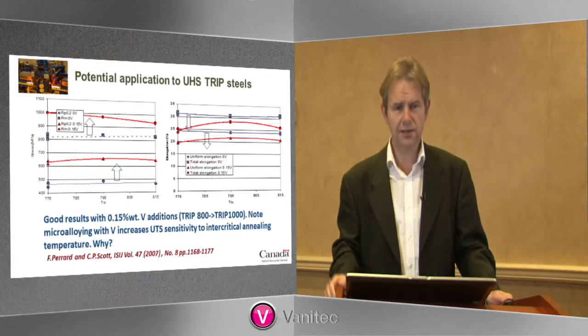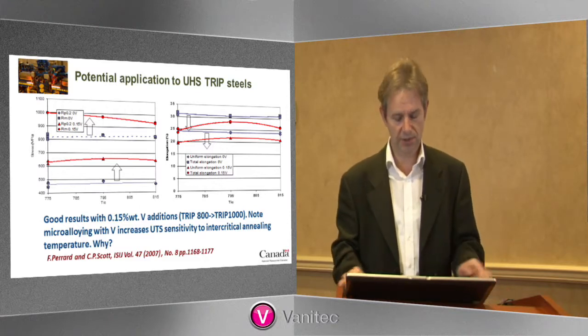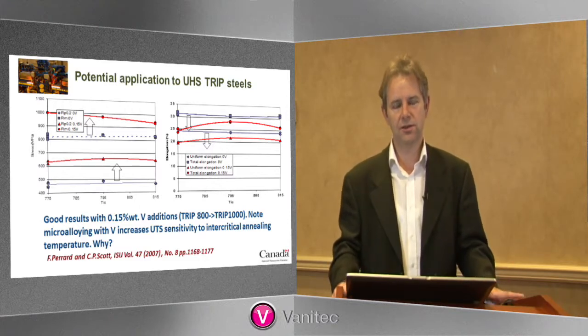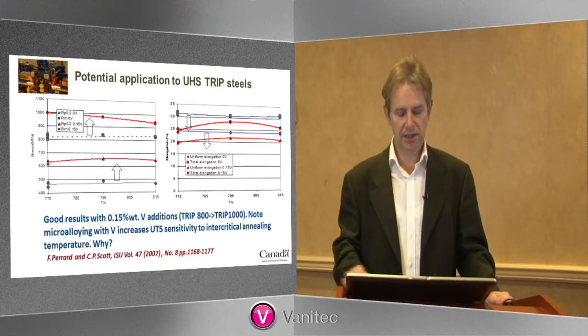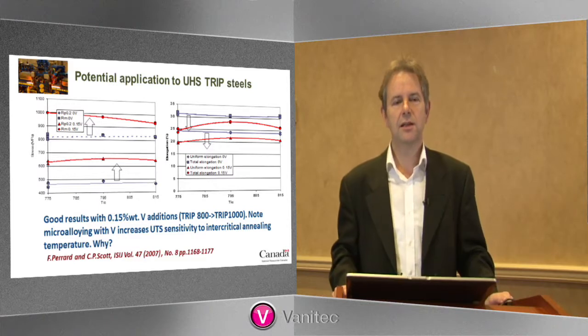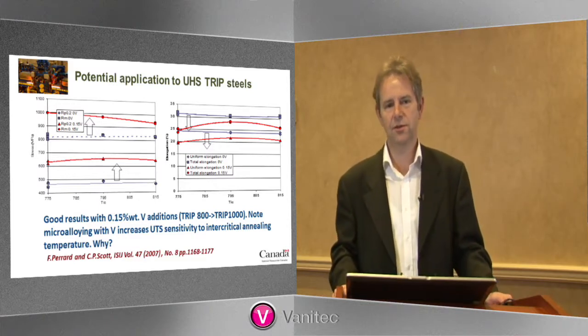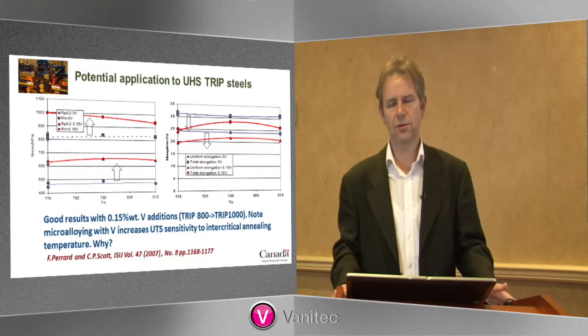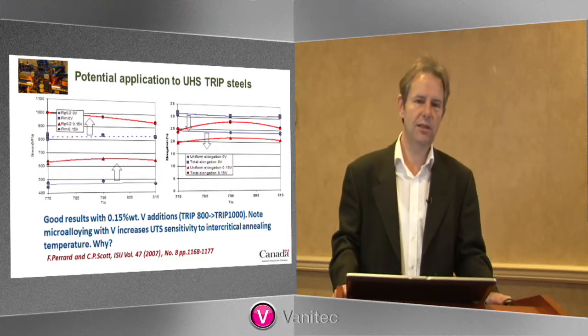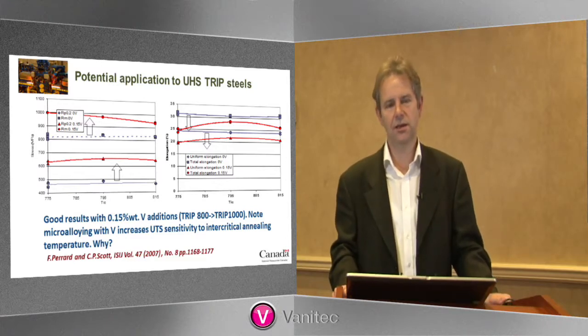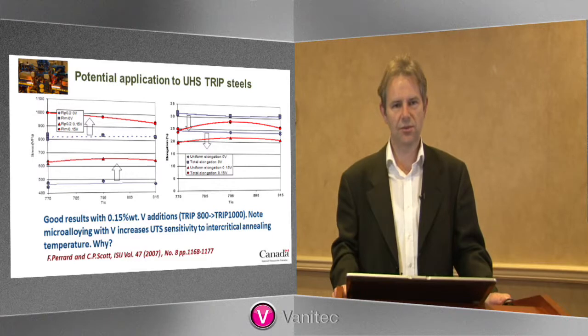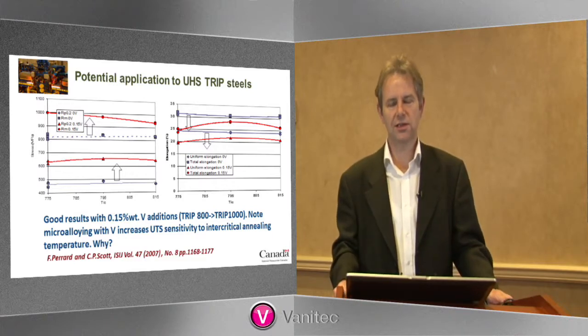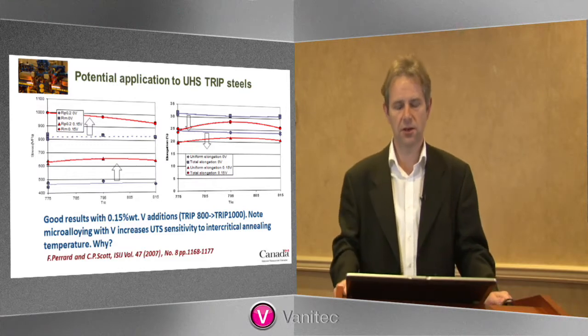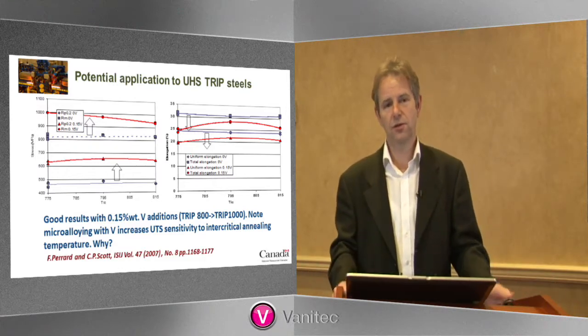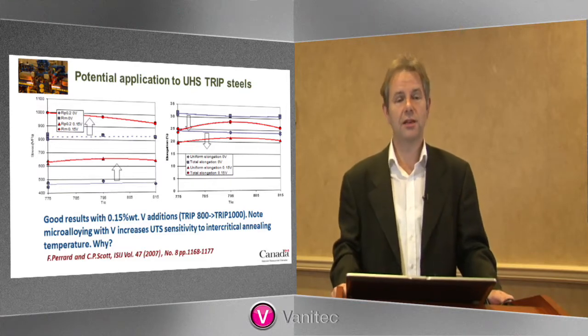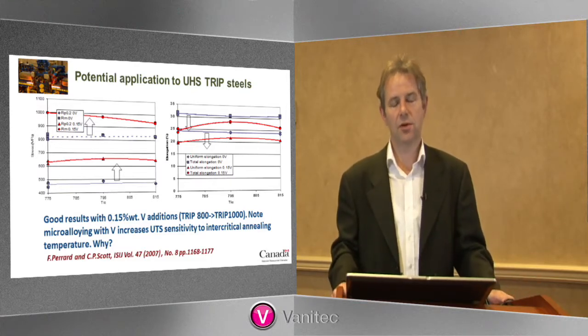good product. The thing I would like to talk to you about later on in this presentation is the sensitivity of these properties to intercritical annealing temperature. You can see, if you look at the left-hand diagram, the yield strength and the tensile strength are not very sensitive to intercritical annealing temperature, over the range 775 to 815 Celsius. But when we add the vanadium, we do see an increased susceptibility, an increased variation in these properties with temperature. And one of the objectives of the study that we did was to actually find out why that occurred. Because obviously if you don't control your intercritical temperature, then you're going to have these potential properties variations.